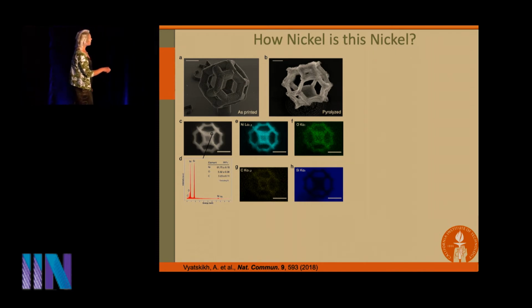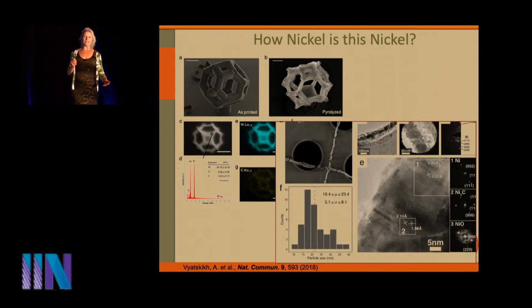So here's the as-printed resin, here's the resin after the pyrolysis, and what we're learning is that there's actually quite a bit of nickel. So this is the EDS spectrum, of course, that shows you that quite a bit of nickel, maybe a little bit of oxygen, but that's not really how we tell the chemical composition or the microstructure of materials. The way we do it in material science is we do TEM, transmission electron microscopy, that allows us to look at the atomic level composition.